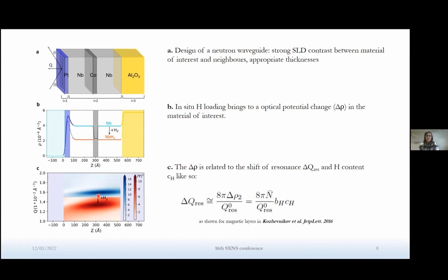And you can see here in the last panel, this is the calculated neutron density versus momentum transfer and depth, and you can see here the resonant enhancement, thanks to the well present here. Now, if we consider a hydrogen absorption into niobium, this will decrease the SLD of niobium, and this will make the well deeper, and this results in a shift in the Q, so in momentum transfer, of the resonance. And so this shift of Q is proportional to the hydrogen concentration through this formula.